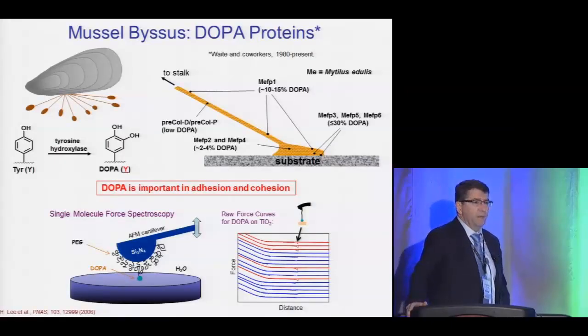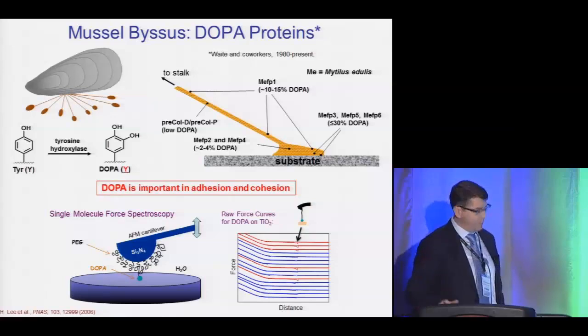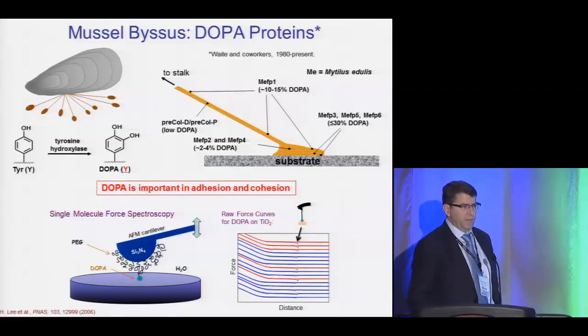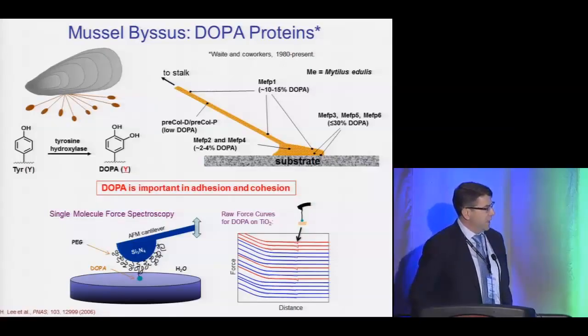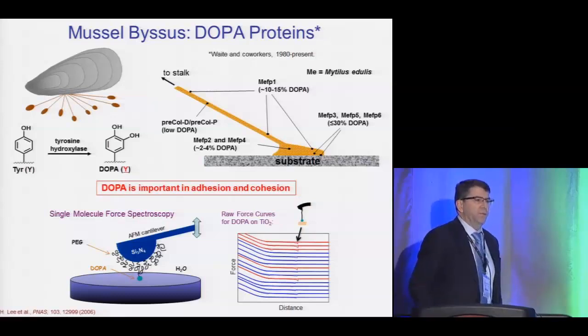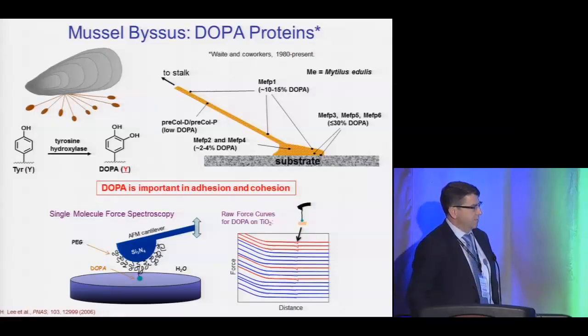One of the methods that we employ is single molecule force spectroscopy. A very oversimplified cartoon of a very complicated experiment is shown lower left here, which is essentially an AFM experiment, not imaging, but rather a force experiment. So we derivatize an AFM cantilever with PEG, which, as you know, would render this cantilever tip probably very poorly interacting with surfaces. And then we attach a single molecule terminal group of one of these chains. And this is one of the challenges of the technique, being able to say that you actually do have a single molecule. But we can do this, and then we do a simple experiment, simple in principle, which is